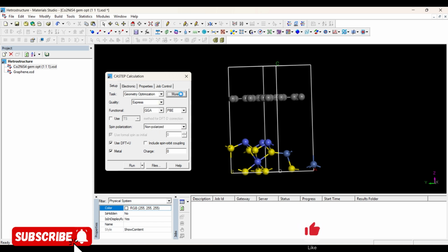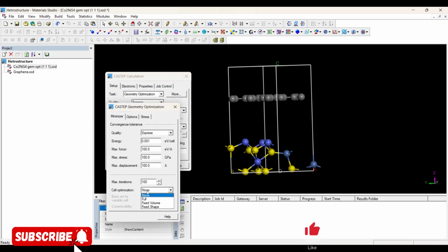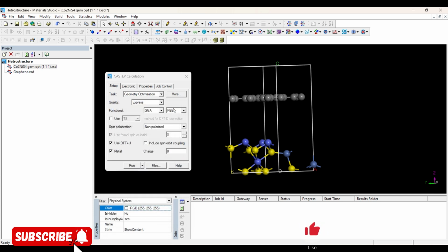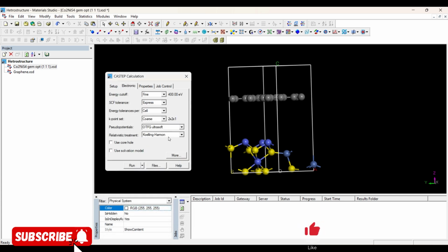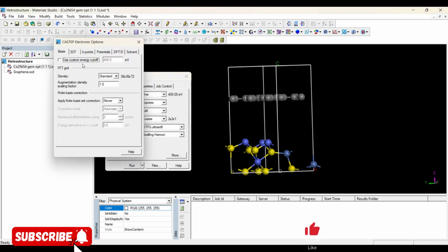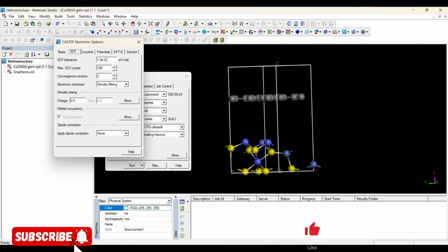Go to more. Here cell optimization should be none, because now we are not going to optimize our cell. We just want to relax our structure within a confined space. So choose none, cross this. Here OTFG ultrasoft is best. Go to more. Custom energy cutoff 500. SCF, this is okay. Choose this value of 500.